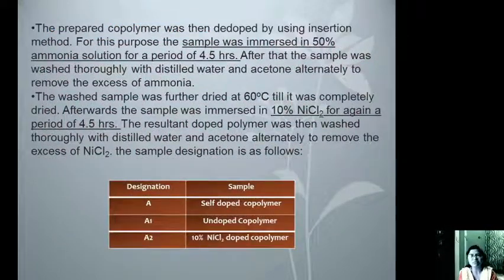The dried sample was then immersed into a solution of 50% ammonia for about 4.5 hours. It was then again washed and further kept in a solution of 10% nickel chloride, and nickel chloride we have used here as a dopant. So the designation of the prepared samples is that A is self-doped, A1 is undoped, and A2 is the 10%